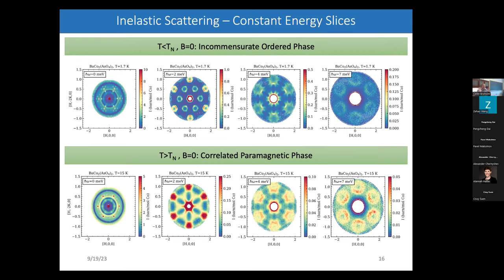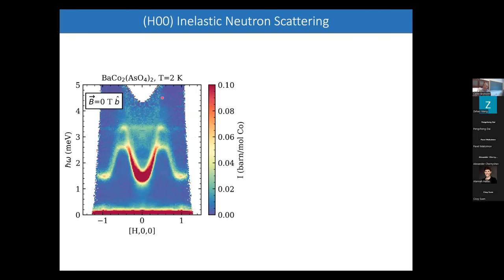So now let me look at the low temperature excitation spectrum in a different way. So I'm looking now at the momentum energy dependence of the scattering, and this is what it looks like. So I'm having wave vector transfer along the gamma m direction, and remember that the wave vector for the ordered state, which still exists actually, is at 0.3. So that's, let me see, this is half, so it's 1, 2, 3, 4, 5. So that's 0.2, 0.4, so 0.3. So this is where the wave vector is actually, but there's no soft mode or anything like that.